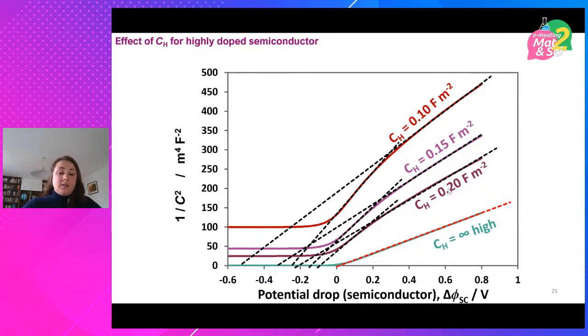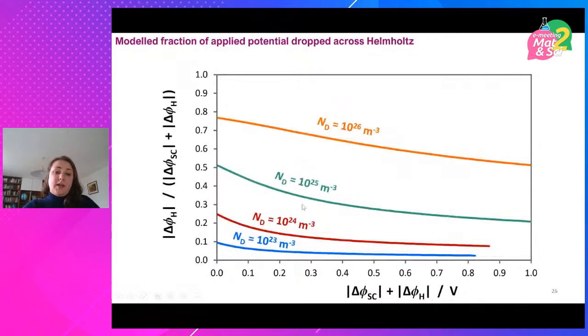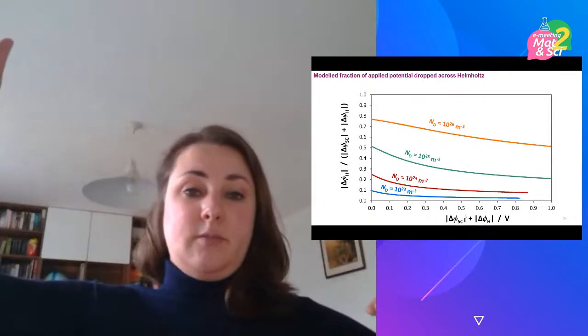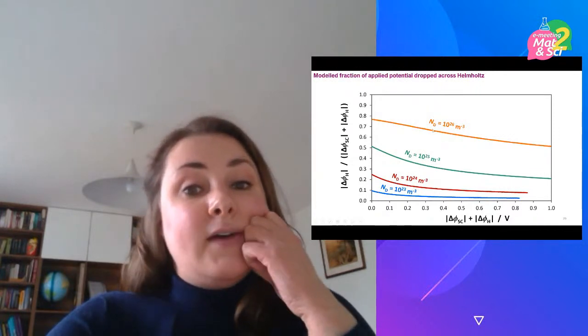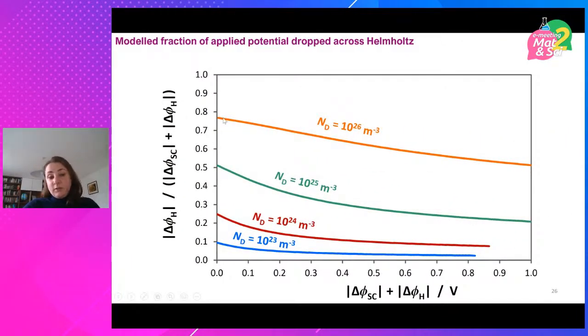cannot be ignored. And the additional factor that also messes with the Mott-Schottky approach is the fact that the applied potential is not distributed always across the semiconductor layer only. So what we've got here is a total applied interfacial bias, so the total applied across the semiconductor and the Helmholtz layer. And on the y-axis, we've got the fraction of that applied bias that goes to the Helmholtz layer. And we can see, unsurprisingly, that the more heavily doped the semiconductor is, the higher the fraction that's distributed across the Helmholtz layer. And that's consistent with the approach to quasi-metallic, to metallic behavior.